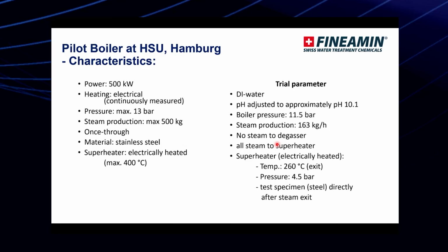The characteristics of the boiler: it has 500 kilowatt maximum power, electrical heating continuously measured, pressure maximum 13 bar, and maximum steam production is 500 kilograms per hour. It is a once-through boiler, the material is stainless steel, and the superheater is electrically heated to a maximum of 400 degrees Celsius.